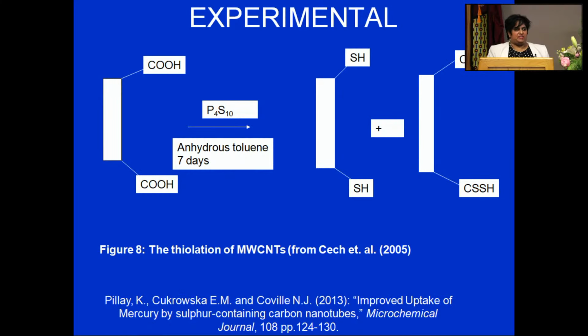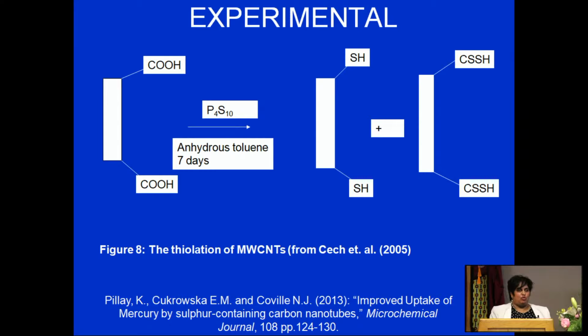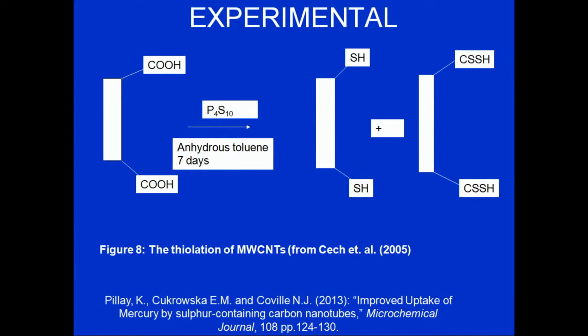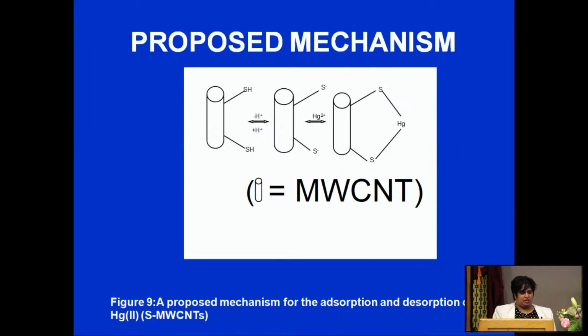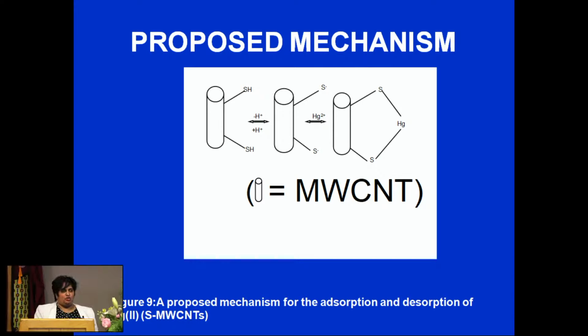As a follow-on study, I attempted putting sulfhydryl groups onto multi-walled carbon nanotubes for mercury-2 remediation. Now, the chemists in the audience will know why I did that, and that's because mercury's got a very high affinity for sulfur, so it's likely to interact with the sulfur on the carbon nanotubes and facilitate the adsorption. So this is the mechanism that we proposed. The sulfhydryl groups are expected to be acidic in nature, so you create sulfur centers that can bind to the mercury ion, but it was only a proposed mechanism at that stage.